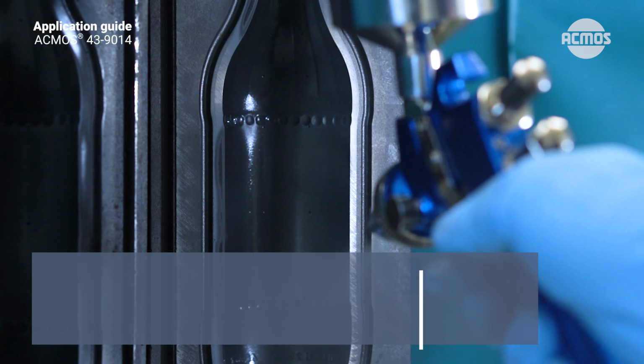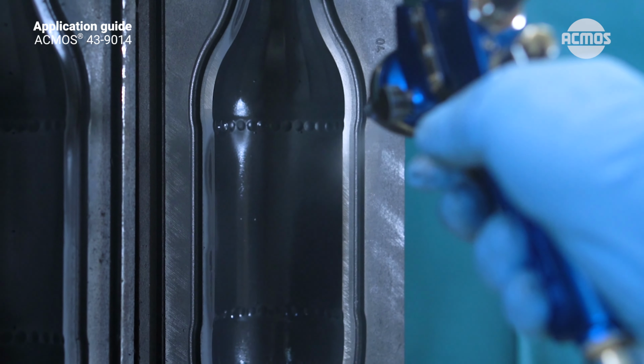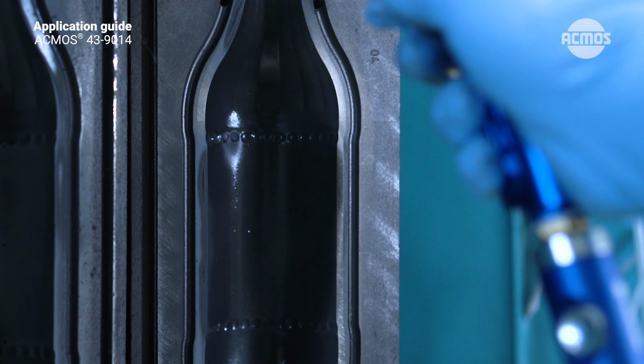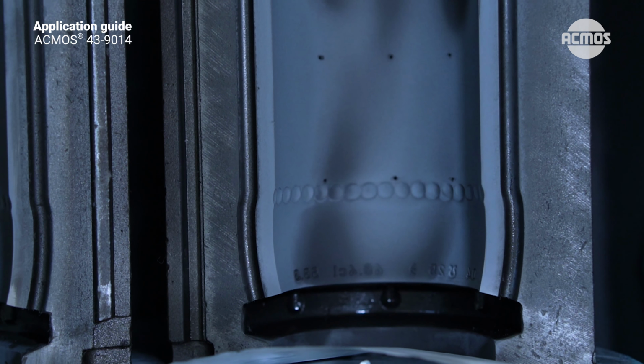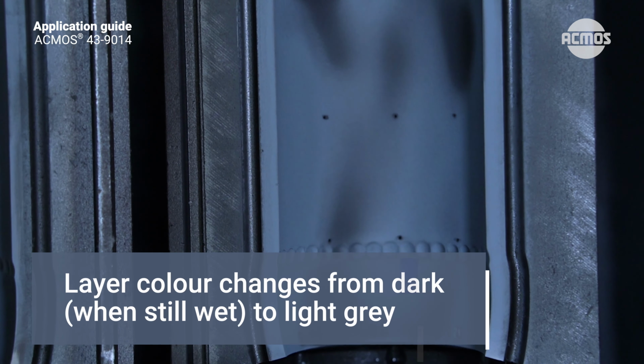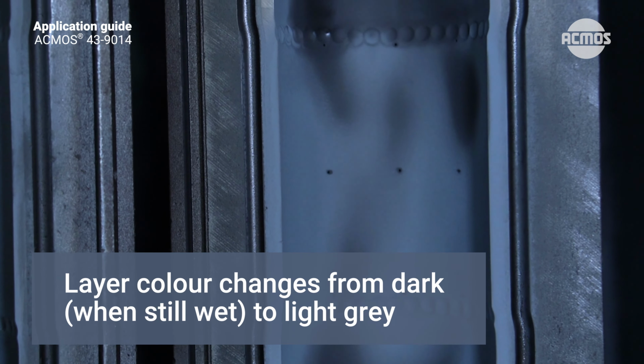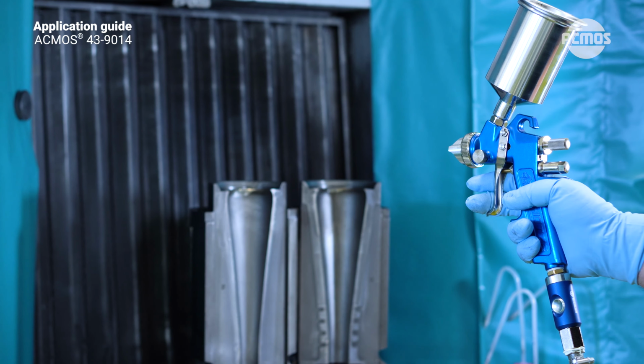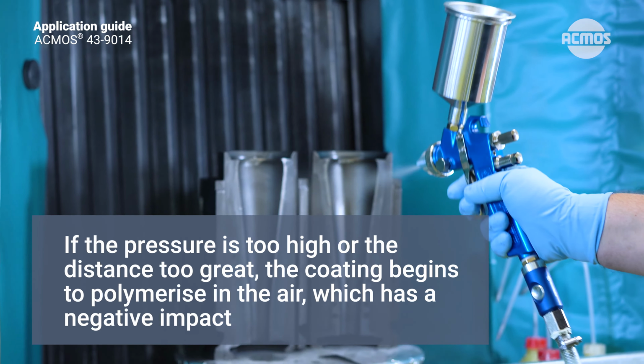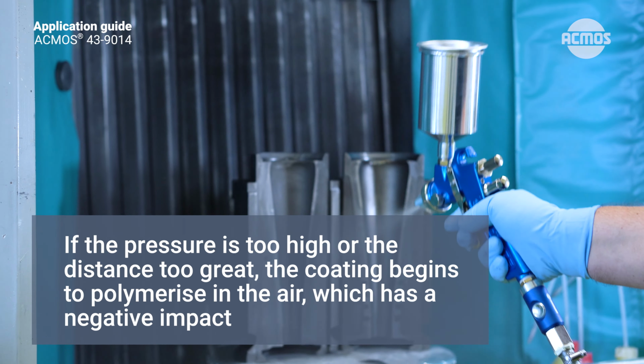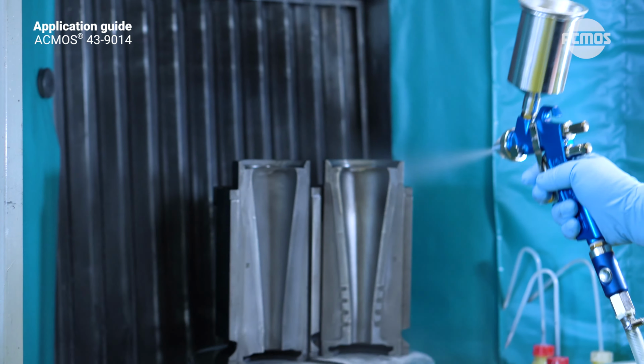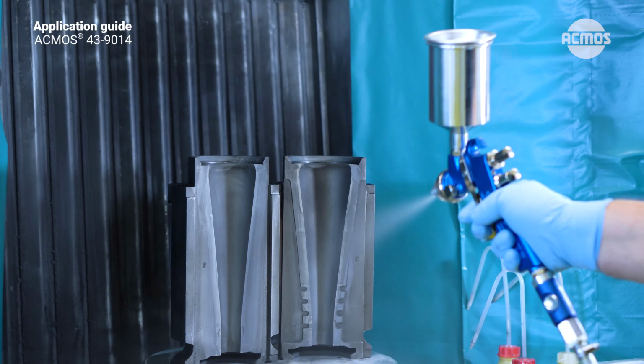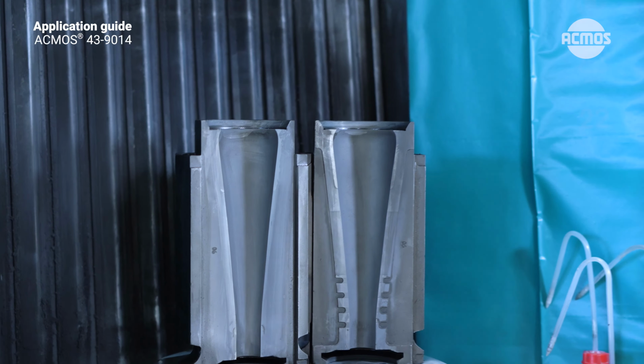The coating should still be wet, forms a shiny, mirror-like layer, and only dries on the mold surface, not before. Drying can be recognized by the layer color, which changes from dark when still wet to light gray. If the pressure is too high or the distance to the mold too great, the coating begins to polymerize in the air, which has a negative impact on the layer formation in the mold and therefore on its performance.